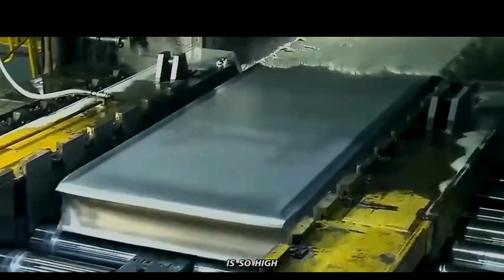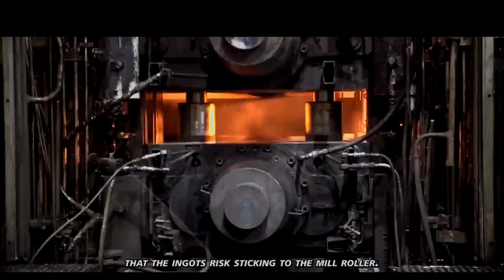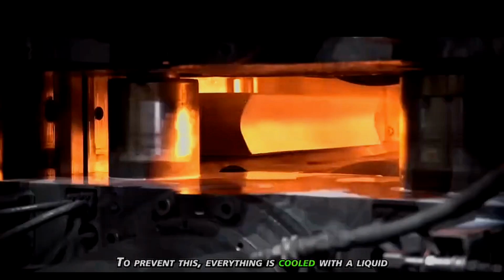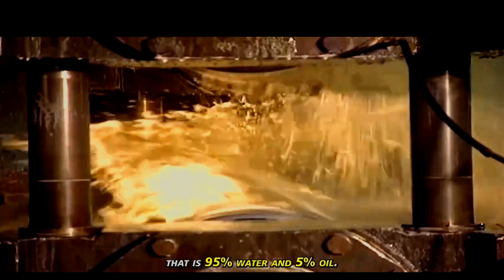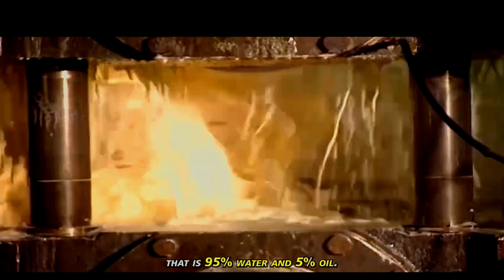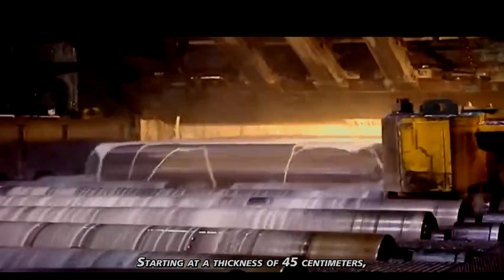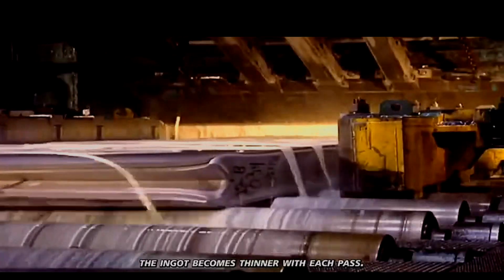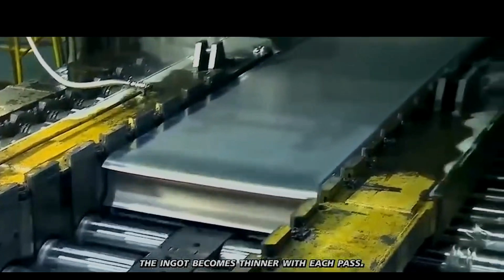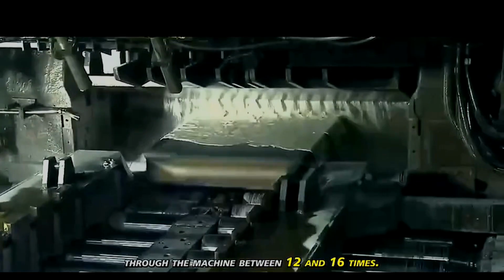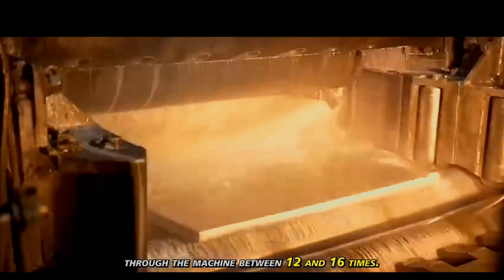The heat is so high that the ingot risks sticking to the mill roller. To prevent this, everything is cooled with a liquid that is 95% water and 5% oil. Starting at a thickness of 45 centimeters, the ingot becomes thinner with each pass. The ingot passes through the machine between 12 and 16 times.